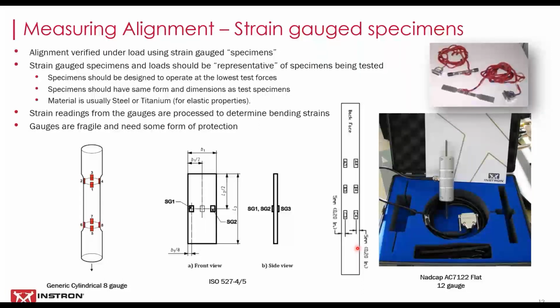These are generally, we try to be representative of the test pieces or the test samples that are being tested. In which case, they should be designed to operate at the lowest force level. But if you're testing metals, it would be the yield strength of the smallest specimen, or its weakest specimen. You try to maintain similar form and dimensions as the test specimens, so that the gripping arrangement is obviously consistent.